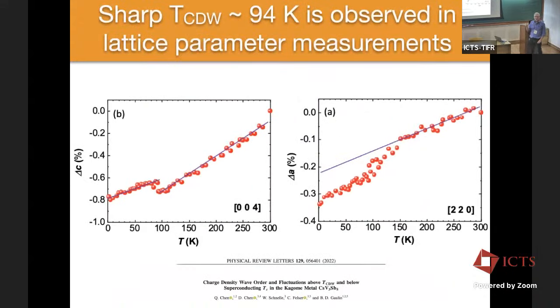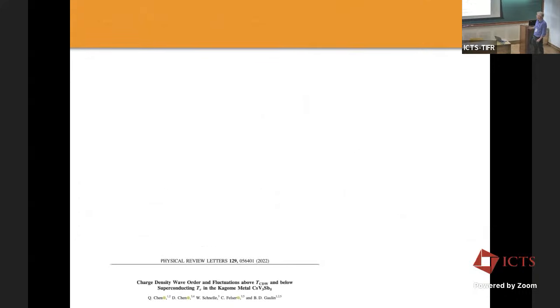So that's not to say that everything that we measured in this low resolution X-ray scattering experiment showed effects due to the charge density wave, which were very extensive. In fact, this is the lattice parameter, which is just the C lattice parameter in the stacking direction. It shows a very nice discontinuity, which is actually pretty big. It's 0.1% at 94 Kelvin, so it's clear that there is a very sharp phase transition here, but it's equally clear that there are fluctuations that go up to much higher temperatures.